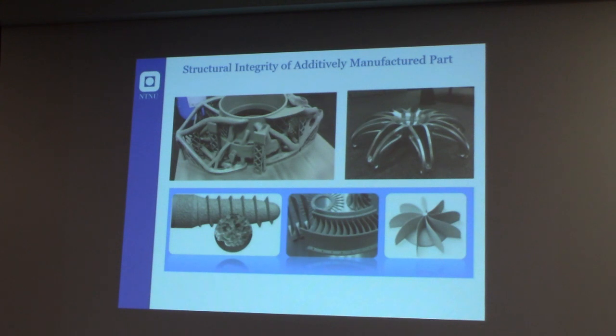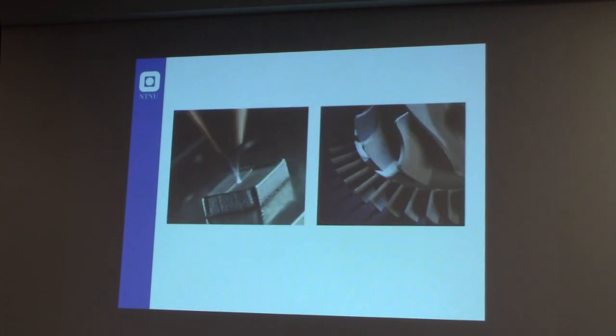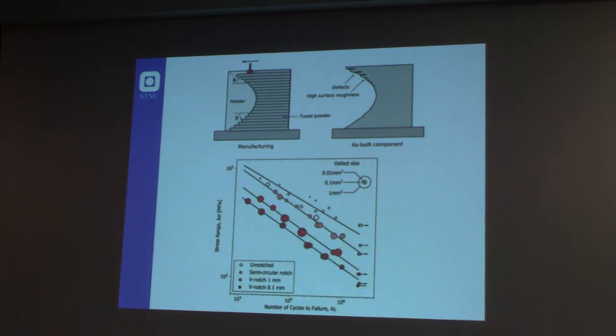In that case, the problem becomes more complex. But I think it's possible to treat it, because the superposition principle is possible if you don't have a large plasticity. And if you are working especially at high cycle fatigue, the plasticity is not so big. So what we did is to start to play a bit with the topic.